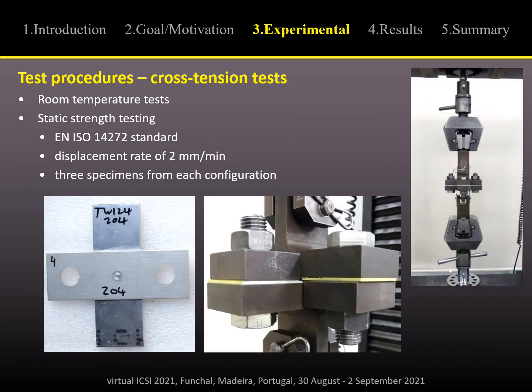And static cross tension or pull out tests were done according to EN ISO 14272 standard under displacement at a rate of 2 mm per minute using 3 specimens from each configuration.